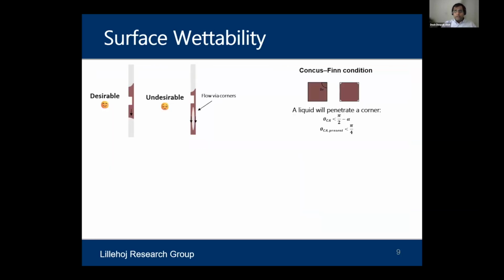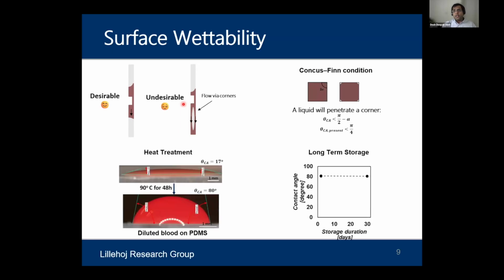So why did we do the heat treatment process? To understand, we have to understand the surface wettability in our device. When we make any device using plasma bonding, the surface is hydrophilic in nature. So for our operation, if you look at it from a surface wettability perspective, we want the slug to fall as a single body. While if the surface is hydrophilic, it would start falling through the corners of the channel, because the channel is square in cross section, and that would change the whole assumption that we wanted the slug to fall at a steady pace. If the slug starts to fall through corners, the flow would be non-uniform. So in order to understand this, the theoretical background is that the surface should be hydrophobic in nature. In order to achieve that, we did the heat treatment process.